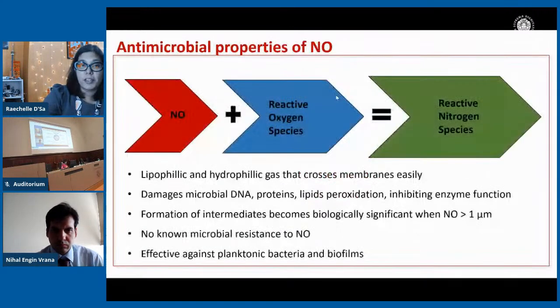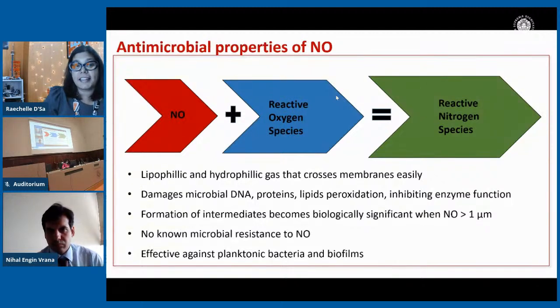So what we do within our lab is we look at the response of nitric oxide as an antimicrobial. Nitric oxide is a lipophilic and a hydrophilic gas that can cross the membrane quite easily because it's a molecule that has a very small Stokes radius and it is neutral. And the way it works is that it forms reactive nitrogen species by combining with reactive oxygen species, and these reactive nitrogen species can then damage DNA, proteins, lipids, and inhibit enzyme function. And it's because there's lots of different ways in which the reactive nitrogen species can inactivate the bacteria that bacteria find it very difficult to develop resistance mechanisms to nitric oxide.